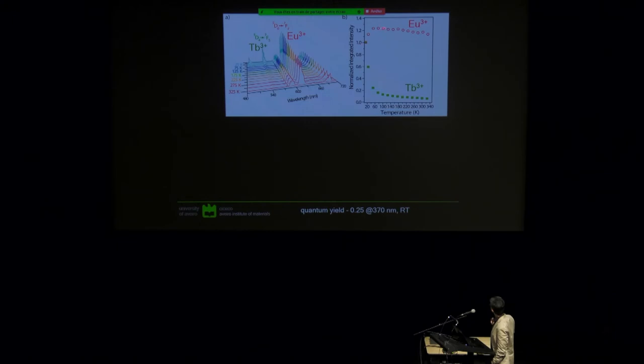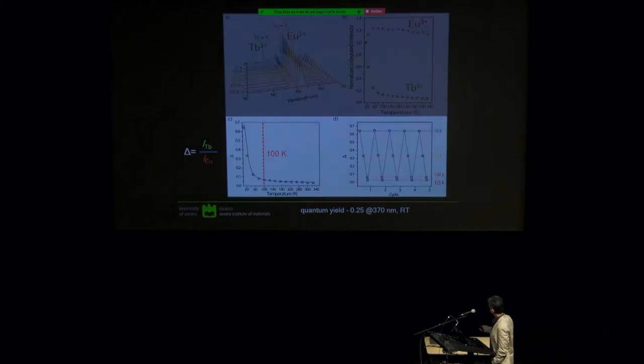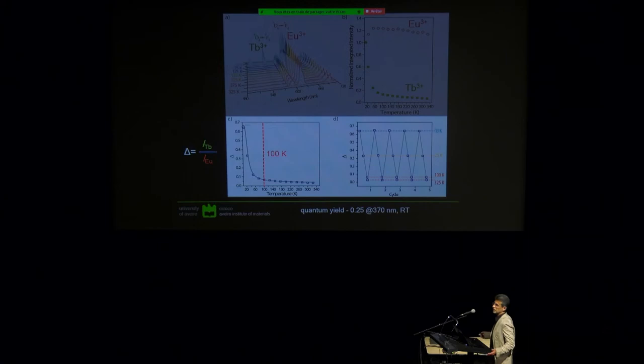And then if you plot the areas of these lines, europium and terbium, and then plot the ratio as a function of temperature, this is what you get. And the ratio of the emissions, you see that above 100 K it doesn't change much, but it changes a lot below 100 K. So we have a sort of calibration curve, we have a thermometer. This particular one is a cryogenic thermometer because it works in the cryogenic range. And you can go up and down in temperature, and it cycles very well. So it's quite stable.